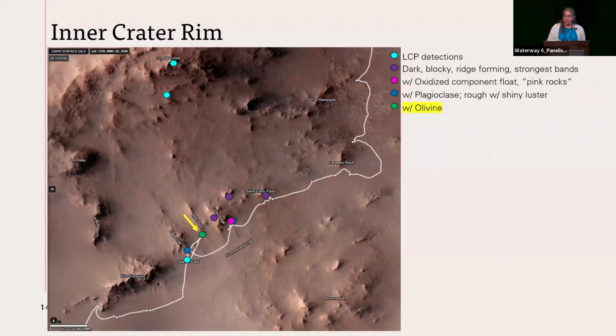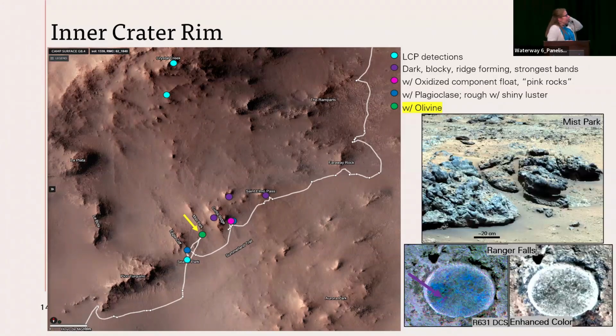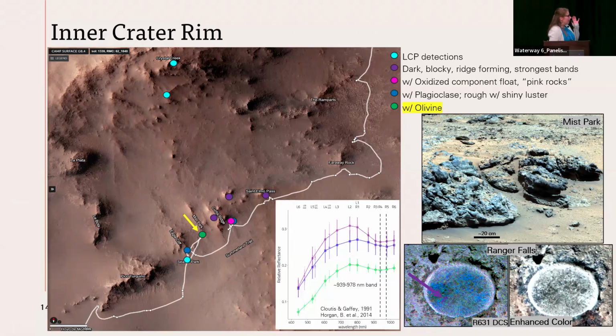And then we also saw low calcium pyroxene mixed with olivine here at Mist Park. A different outcrop yet again. So hopefully you can see the different expression of this outcrop, this almost lobate looking expression, is different from the blocky outcrops we saw at St. Elmo Pass and Curtis Ridge. But again, this is olivine dominated, but does have low calcium pyroxene in it, which we saw in the abrasion patch and with other instruments. And the spectra seem to bear that out too.